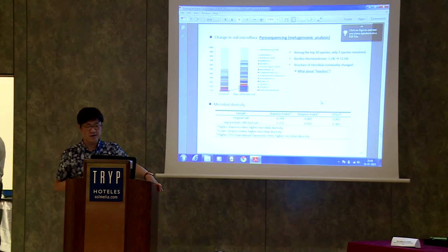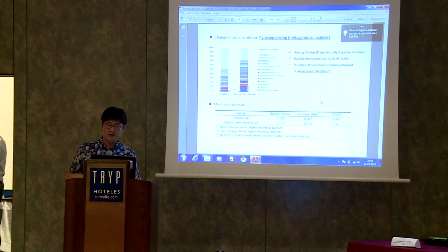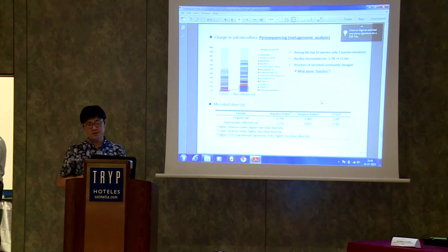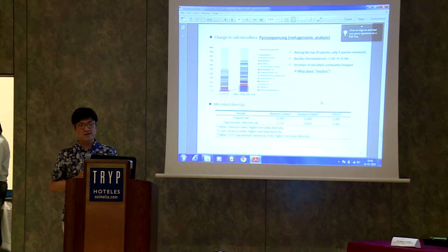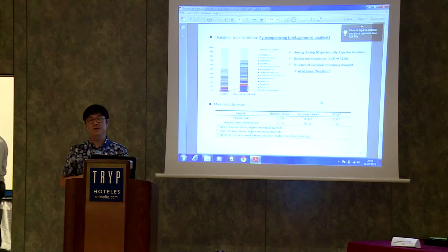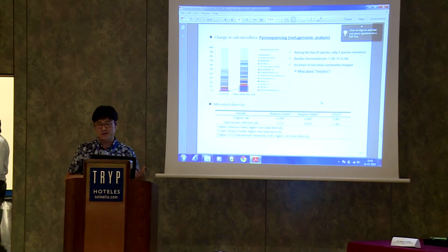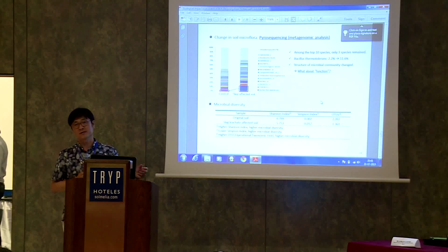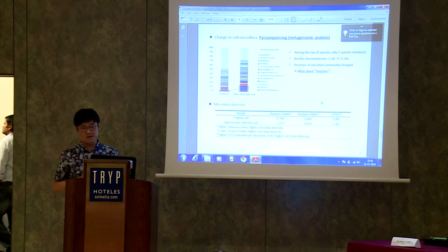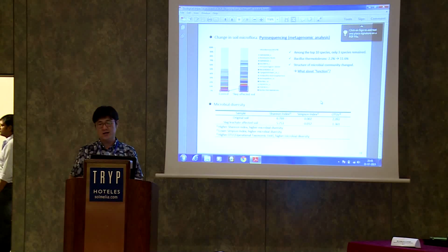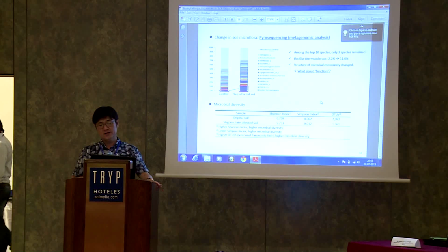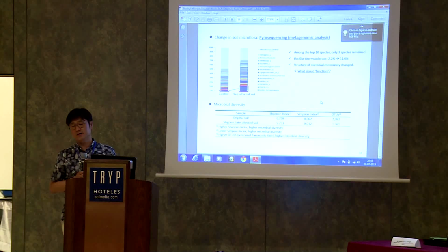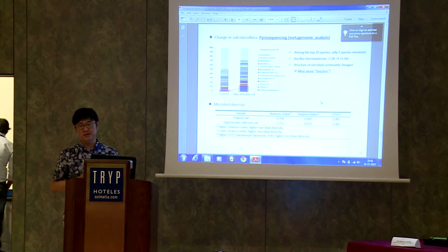And also we performed the pyrosequencing, meaning the metagenomic analysis of the soil microflora by using DNA techniques. Among the top 10 microbial species in the original soil, only 3 are left in the slag-affected soil, which means 7 disappeared during the experimental period. It's about a 100-year simulation. And mostly Bacillus thermotolerans, the population increased from 2.2 to 11.6%. So this clearly shows the structure of the microbial community changed with the slag leachate.